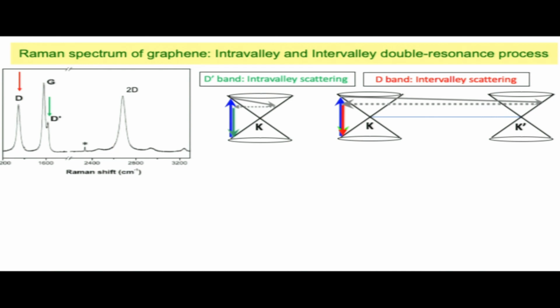It's like if I send a ball in, the ball will come back. That is one elastic process. Then when we have a defect to scatter the electron back from this point to that point, I have the D band. But you see that in this case, the D band involves the Dirac cone K and the Dirac cone K prime. That's what we call inter-valley scattering, because the electron is scattering from one valley. I say that when the electrons are in those cones, they are in a valley K. They're scattering from one valley to the other valley here.